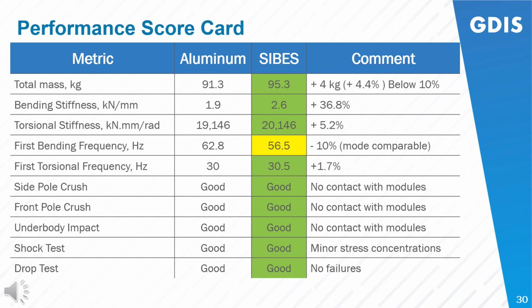The steel concept that was developed, again, showed very minor stress concentrations in the shock test that could be easily handled through refinement. Unfortunately, because of the time constraints, we weren't able to continue to refine this, but we are very confident that this could be easily addressed if needed.